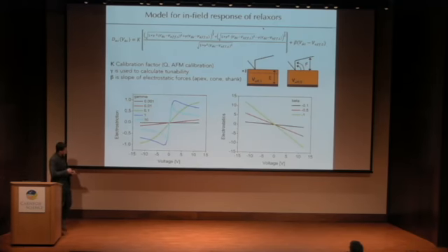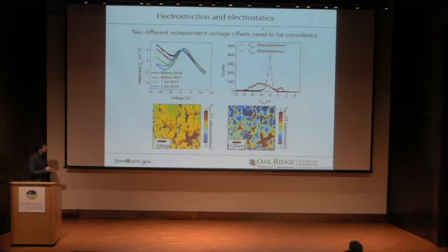What you see here is a simulated response that we expect to see from this film as a function of increasing parameter gamma. As you see on the next slide, gamma is related to the dielectric tunability of the material. Lo and behold, the experimental data that we are observing looks quite similar. We had this sigmoidal shape of the response, sometimes with a slope. Because the model decomposes into electrostatics and a tunable part, with some reasonably frivolous choice of fitting parameters, we were able to fit these curves quite reliably.